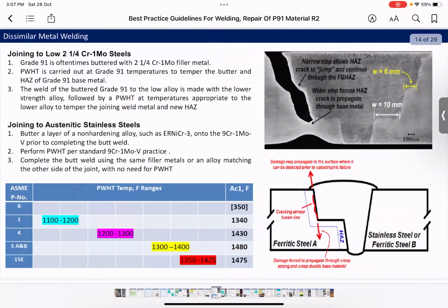For dissimilar weld joints, one of the important things that we should do is the step bevel. This step bevel is very important, not only in the dissimilar weld, but also for thick components. We should also use this step bevel. The reason is that the susceptible area for having a crack is the heat affected zone. This is because of the fine grain structure or the soft area that can have type 4 cracking in P91 material. So the location where the crack can initiate is within the heat affected zone.